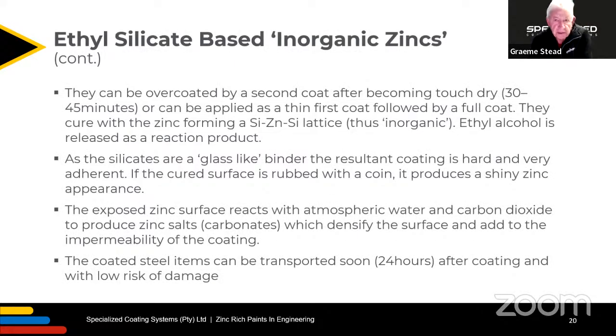They can be overcoated by a second coat after becoming touch dry, 30 to 45 minutes, or can be applied as a thin first coat, followed by a full coat. They cure with the zinc forming a silicon zinc silicon lattice. Thus, the inorganic nomenclature, and ethyl alcohol is released as a reaction product. So there's no carbon in the resultant film. As the silicates are glass-like binder, the resultant coating is hard and very adherent. If the cured surface is rubbed with a coin, it produces a shiny zinc appearance.